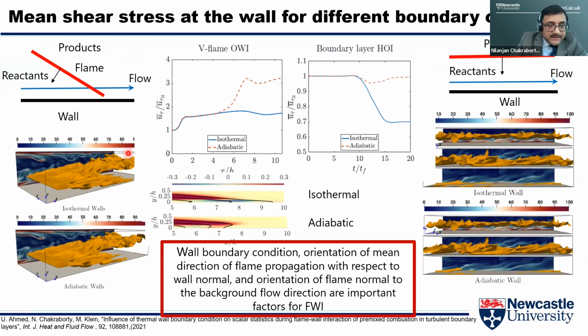You can see from the isosurface here that the flame is stretched towards the streamwise direction in comparison to the adiabatic wall. If we look at it in an average sense, you can see these isosurfaces of reaction progress variables are bent towards the upstream. What really happens, reaction rate is 0 on the wall for the isothermal case. For the adiabatic case, reaction can actually take place on the wall surface. As a result, the flame tries to go upstream, but in this particular case, the upstream flow is greater than the laminar burning velocity so that it cannot propagate.